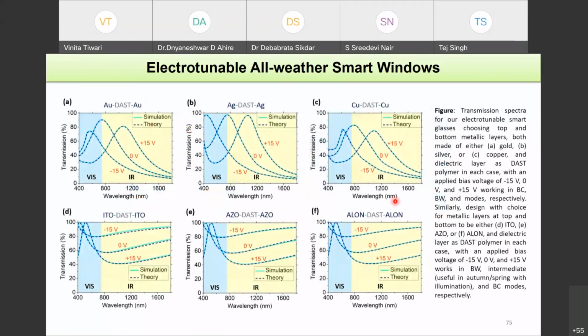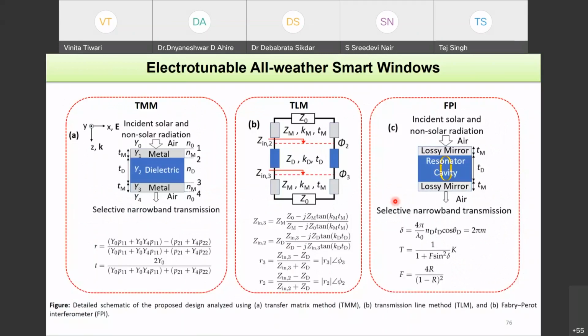So I'm skipping this, and coming to the theoretical part. You can again apply the transfer matrix method for your metal dielectric metal interface, and you can obtain the reflection coefficient and transmission coefficient. So you can understand that this transfer matrix method is a very useful tool for modeling all these different multi-layer structures. You can also use the transmission line method, and you can do the impedance matching and finally come up with the reflection coefficient and transmission coefficient.